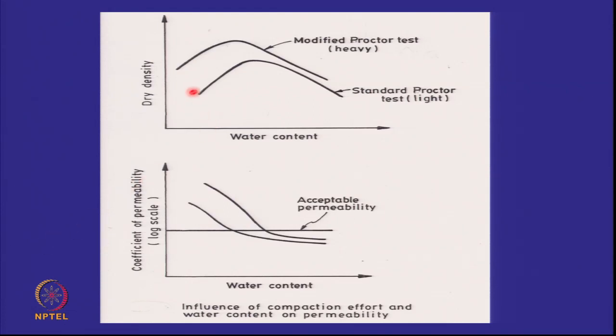I will have to do these permeability tests at different points along the Proctor curve to see how the permeability varies with the water content. So this is the standard Proctor test, this is the modified Proctor test. So I may take 5 samples, 1, 2, 3, 4, 5. And when I have these 5 samples, then I can get the permeability values, and this will show you that the permeability will decrease with water content. This curve has lower permeability than this, so this corresponds to the modified Proctor test. This is for the standard Proctor test.